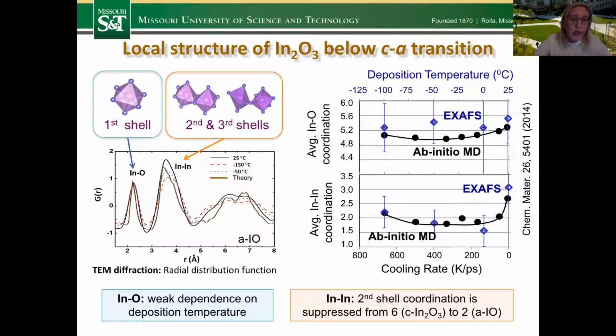And here I compare the experiments just around the peak, so 25 degrees, slightly above, and then 2 data points that are below the mobility peak, as well as theory. What we can see is that the first shell peak is showing very weak dependence on the deposition temperature. The position of the peak does not vary that much. There is some broadening, of course, but generally the first peak survives.